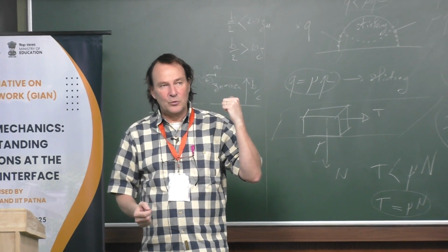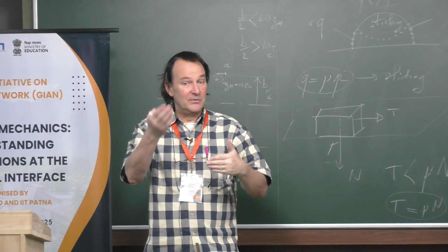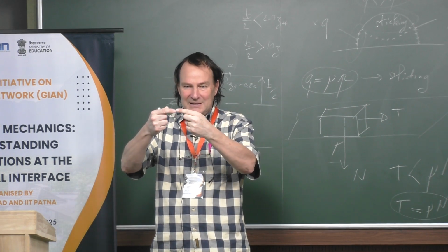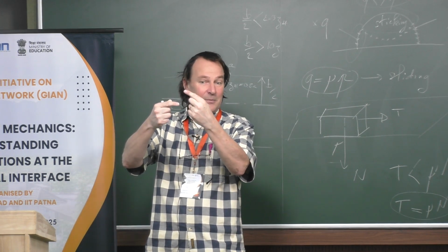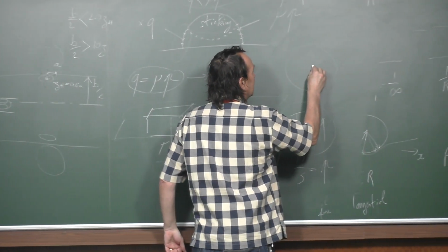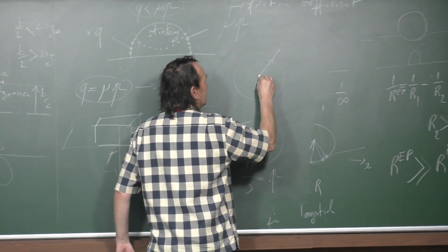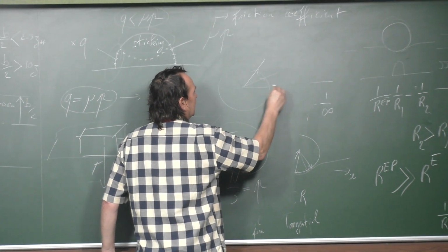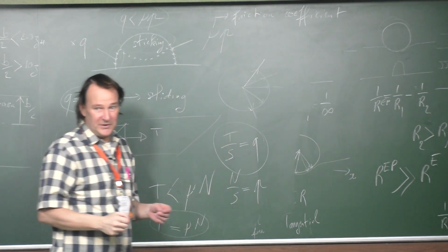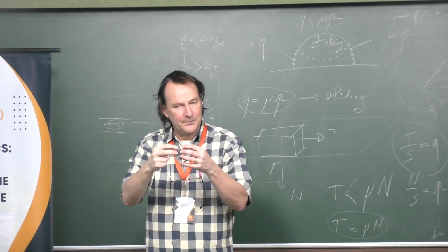But now, because we have a composite material and a steel material in front of it, when the two points are touching each other, they are sliding because stiffness is not the same. Normally the displacement is radial, like that. This is the relative displacement or relative sliding between the two surfaces.